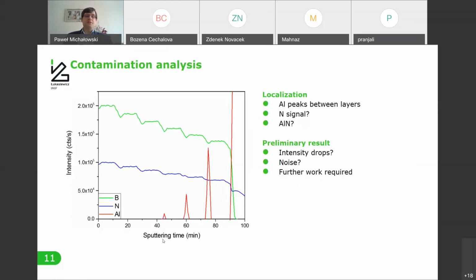Okay, but we also made additional analysis about the contamination in this layer, particularly in the case of aluminum. This is one of these preliminary results that I still need to work on. As you can see, for each boron nitride layer, I see some drop of the intensity. Once again, you can see exactly 6 boron nitride layers. What was also important is that we see some aluminum peaks residing exactly between the layers, and at the same time, whereas the boron nitride has a clear decrease here, the nitrogen, okay, this is not perfect, this is still somewhat noisy. There are some decreases in the first layers, but later, when we see these aluminum peaks, this decrease is not as well pronounced as here.